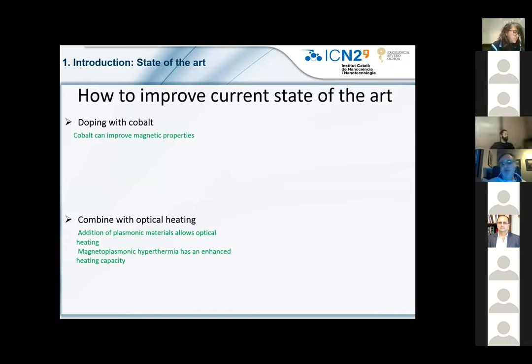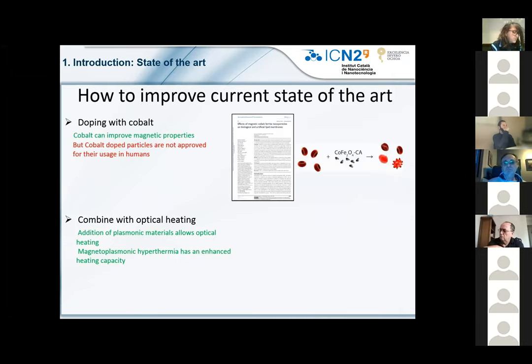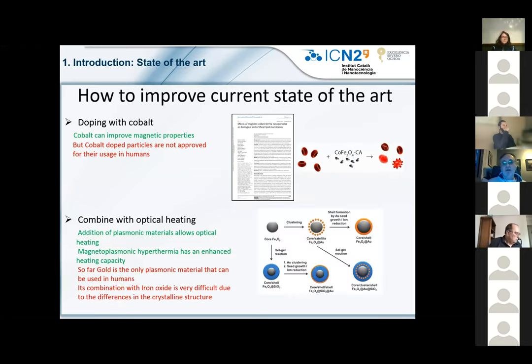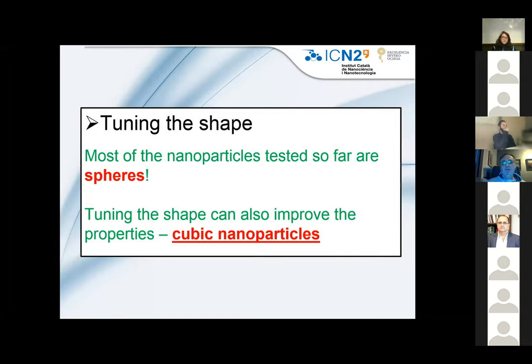Another possible way to improve is combining optical and magnetic heating, which is usually done by adding a plasmonic particle to the magnetic particle. What's the problem? Cobalt-doped nanoparticles are not approved to be used in humans, so that puts a lot of limits. And gold is the only plasmonic material that can be used in humans, and its combination with iron oxide is quite complex because they have very different structures. So creating core-shell nanoparticles, for example, or dimers is not trivial. Another way to tune the magnetic properties is to tune the shape. So far, most of the studies have been carried out in spherical nanoparticles. Tuning the shape can also improve the properties, and what we are going to tell you about today are cubic nanoparticles.